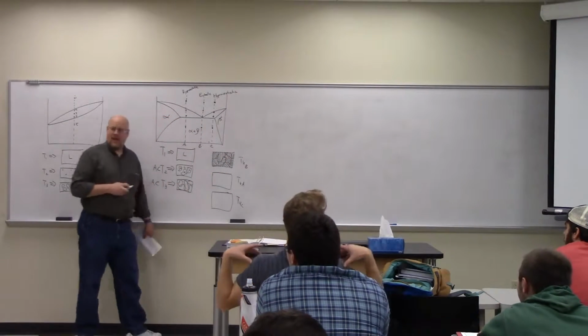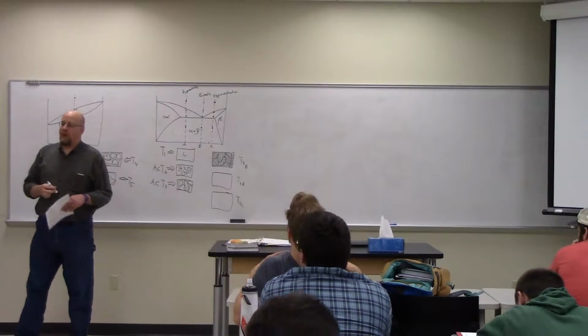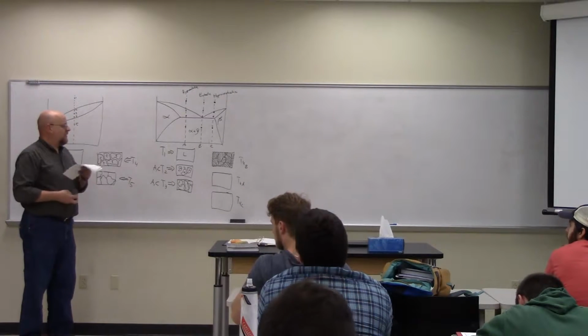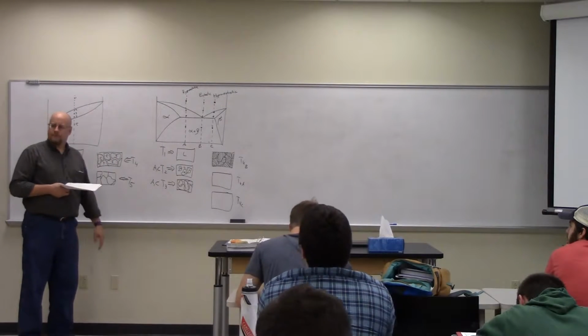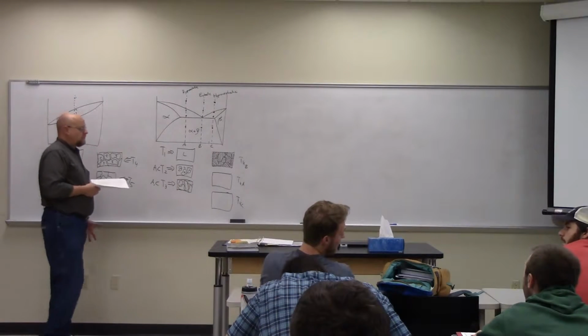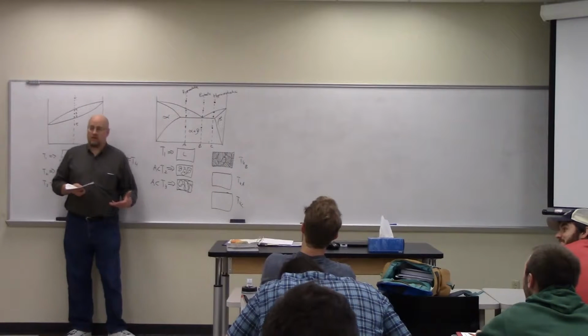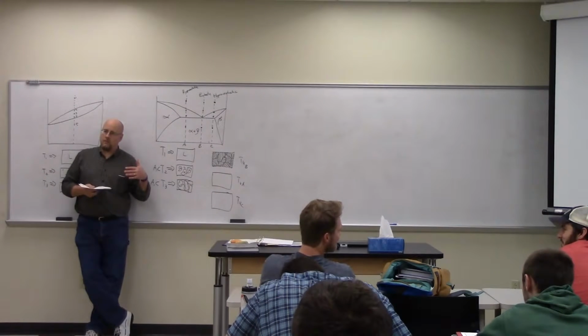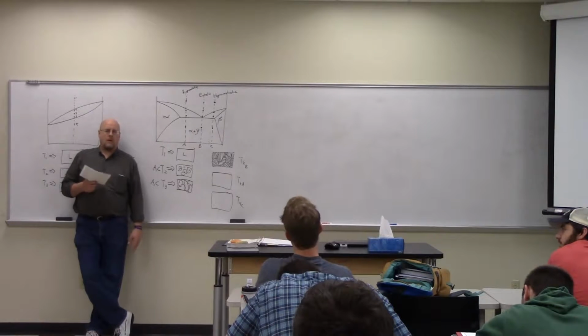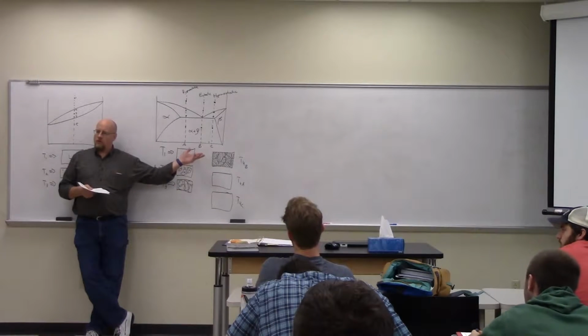Okay, you get that, where the dark spaces are alpha and the light spaces are beta. The lines like that? Actually, yeah, it's actually plates. They're plates, but I'm slicing them in half, so I'm seeing the lines. It's what we call a lamellar structure.